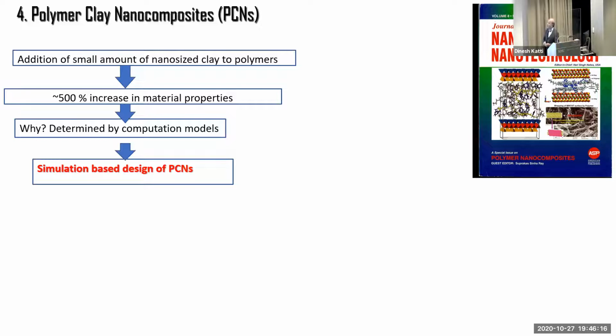Now, the last nanocomposite material that I'm going to talk about are polymer clay nanocomposites. When you add small amounts of nanosized clay, we are talking about 1 to 10% or less, small amounts of nanosized clay. And the key is nanosized. That's important. If you add small amounts of nanosized clay in a polymer, polymer could be nylon or polyethylene, the common polymers, there's a 500 to 600% increase in the elastic modulus or the stiffness of the material. So why is it that when you add very small amounts of nanosized clay, we see this huge jump in mechanical properties of the composite? Well, polymer clay nanocomposites were developed by Toyota Motor Company in 1990. And really nobody knew why this happens.